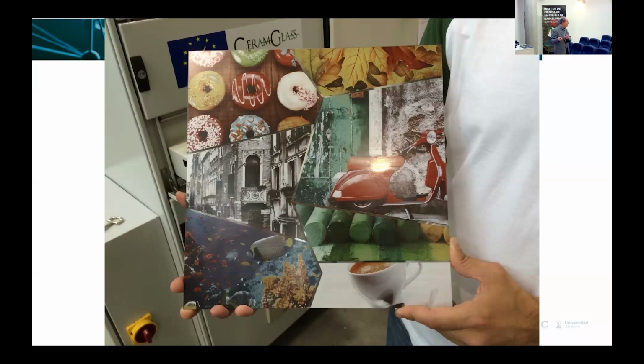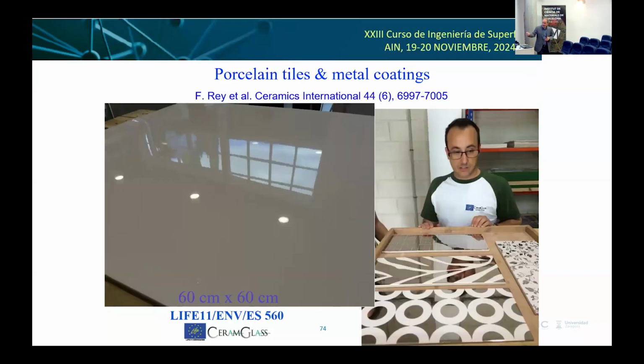And we can integrate any coating into it. So then this is a ceramic, 60 by 60 centimeters, and you can see how good the surface finish is. In fact, we can reach values of about 40 nanometers roughness, which is really nice. And this is a coating of a metal. So we are metallizing a coating which contains an organic metallic salt, and it gives you the metal. Usually, unfortunately, it's a very expensive gold, platinum, or something like that. But there are customers who like that.